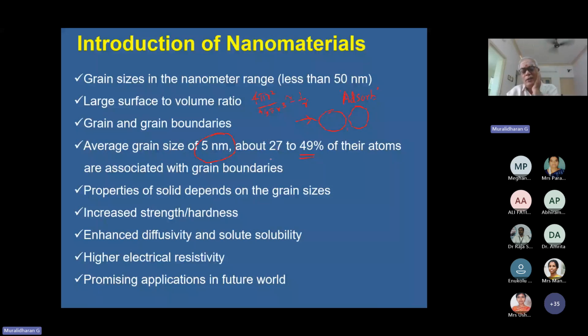We may ask, sir, is it always advantageous that all the atoms are sitting on the edges? The answer is certainly not yes. They are not advantageous because all these atoms are sitting on the edges. They are so reactive that when you make a material of average grain size 5 nanometer, prepare it today, measure the dimensions, and keep it stored for about a month, measure the dimensions, store it for 6 months, measure the dimensions. You will see that progressively the dimensions will increase. It may go from 5 nanometer to 10 nanometer when you store it for 6 months. That's because of this strong reactivity.